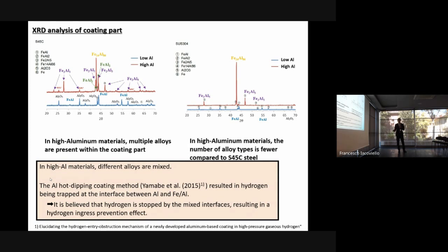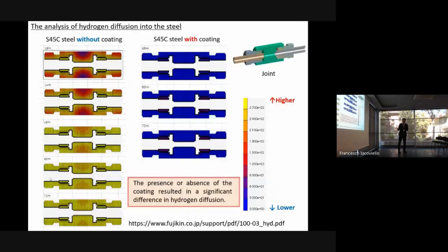In previous reports from Professor Yamabe, the aluminum hot dipping coating method resulted in hydrogen being trapped at the interface between aluminum and the FeAl alloy. Hydrogen was trapped, preventing hydrogen ingress. So from this paper, it is believed that hydrogen is stopped by the mixed interfaces, resulting in a hydrogen ingress prevention effect. But we want to do further investigation about it.